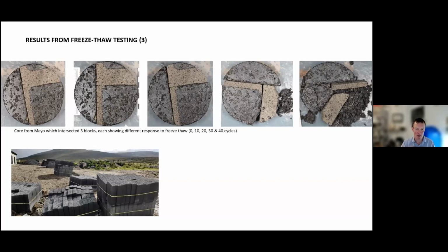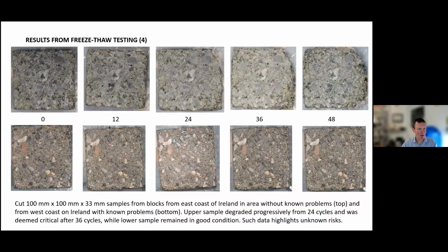We assume they all had the same cement content, the same aggregate, but you can see different responses. And I postulate that this is due to some preconditioning, possibly storage on site and wetting, drying, or possibly freeze thaw before the blocks were put into service. The worrying thing is that if you take new blocks from around Ireland and blocks that do not have an abundance of mica or pyrite in them, some of them are durable and a few of them are not. So here we see two cases, the upper one from the East Coast, no known problems in the area, but you can see after 36 cycles, it's looking pretty ragged. The lower one is better.